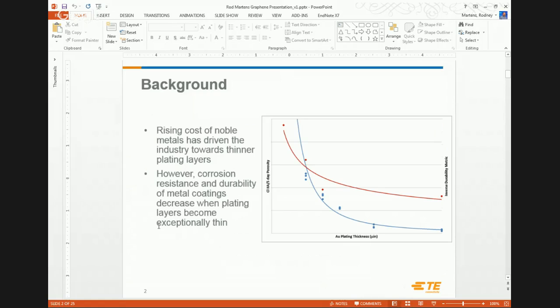One thing I want to mention is that if you look at a connector, your phone charger, you'll see a little glint of gold in there. Now, why would we use gold? I think gold's a fantastic material for what we want to do because it's corrosion resistant, it's thermally conductive, it's electrically conductive. You add about 0.5% of cobalt or nickel to it, and it's actually quite durable and low friction. So we don't use it because it's pretty. We use it because it really helps enhance the properties of an electrical contact.